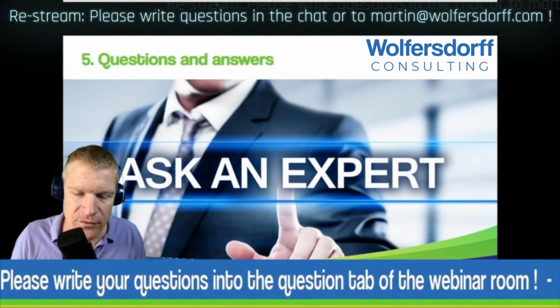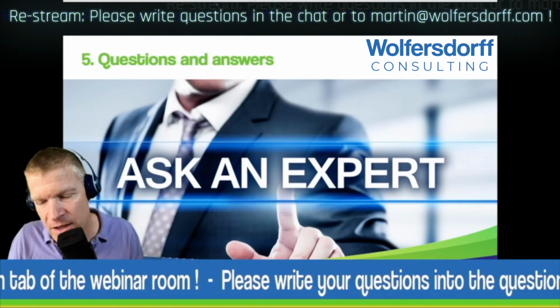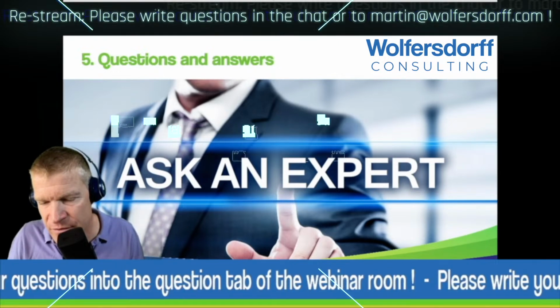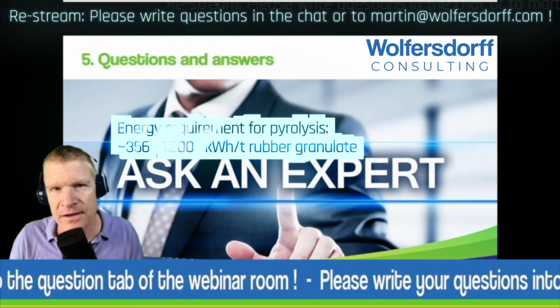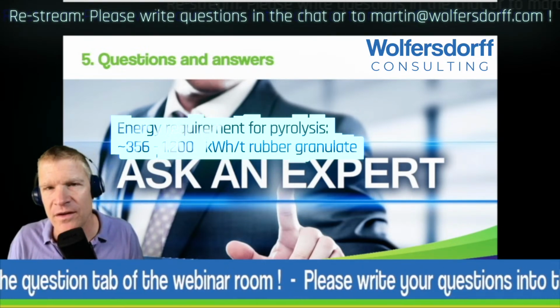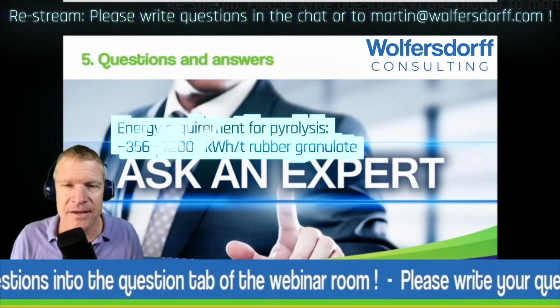And the last question, also from Derek: do you have data that you can share about the carbon dioxide savings from using RCB? Now, I quoted the master batch companies and the carbon dioxide saving they advertise. You might understand that the carbon dioxide burden of the recovered carbon black also depends on the thermal efficiency of the process. So what I see, if you have a batch discontinuous process, I see values of 0.4 tons carbon per ton of recovered carbon black, which is already 2 tons less than the virgin carbon black. And I see 0.2 tons of carbon dioxide burden in the case of continuous processes.